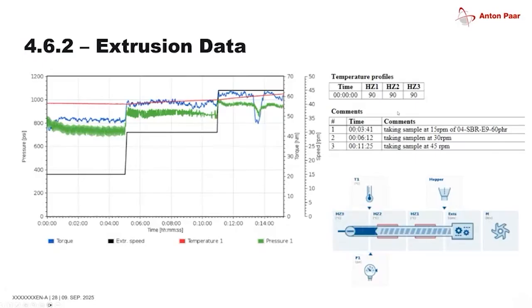Then you can add comments and set your temperature profile. All of that will be one printout at the end of the test, where you can compare the data. Here you see this was at speeds 15, 30, and 45. You can see how the pressure, the green line, jumps, and how the torque jumps. And obviously, as we put more mechanical energy into the system, our temperature is also slightly rising. With increased temperature, our viscosity typically drops.